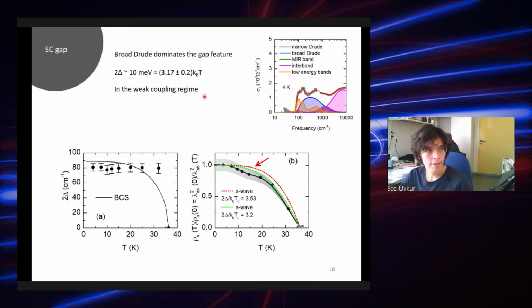And this was kind of a question mark, because now we have a gap in the weak coupling regime. It's a multi-band system, so there should be another gap that is in the strong coupling regime, but we don't see it. I will come to that point maybe in the next slide. But we could only observe one gap at that time. We plotted the temperature dependence of the gap value and then the temperature dependence of the superfluid density, which you can directly convert from the missing area in your spectrum.